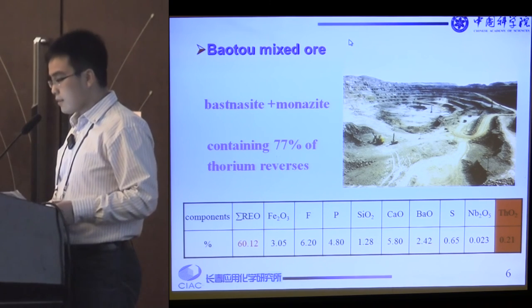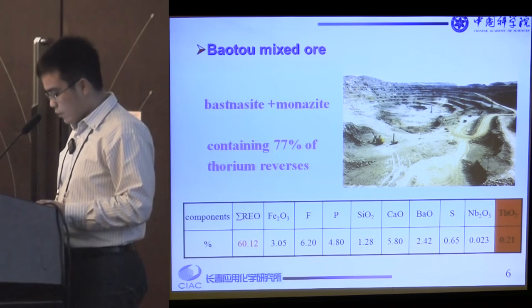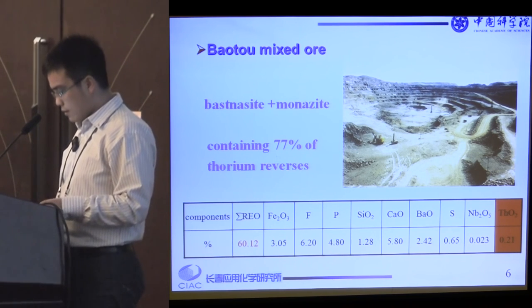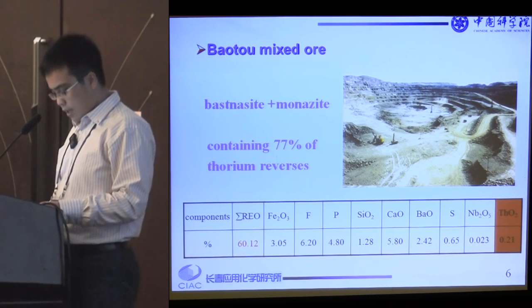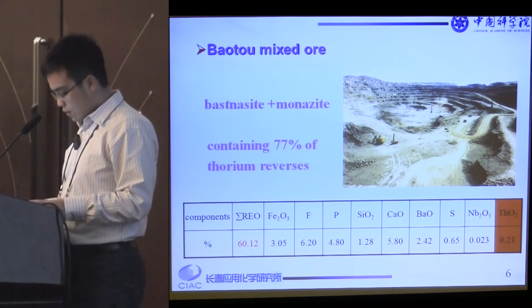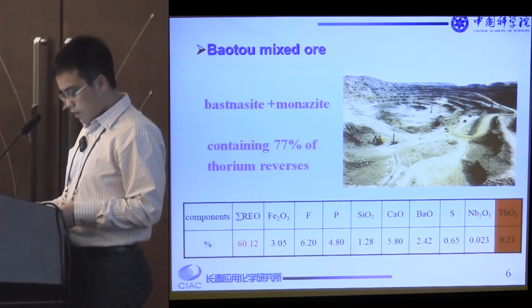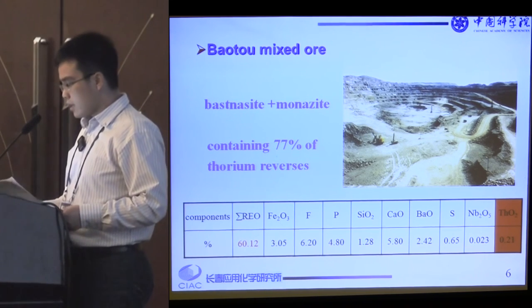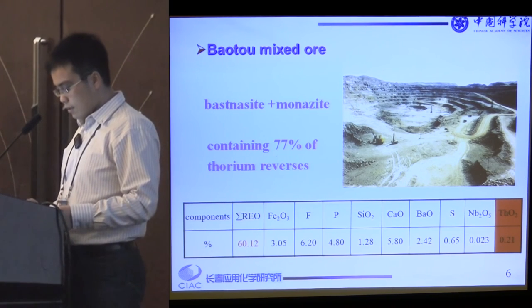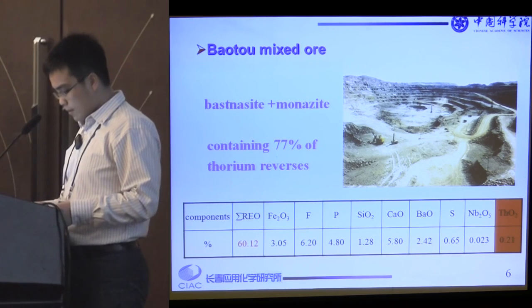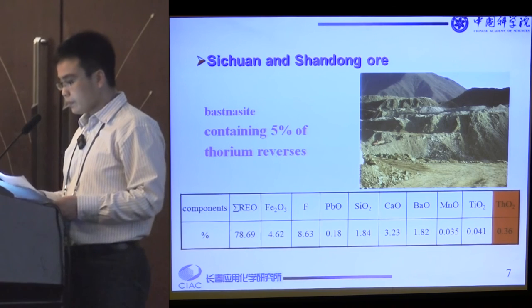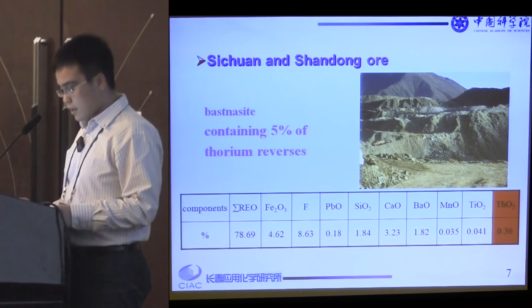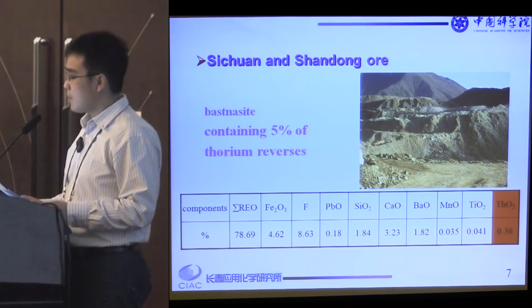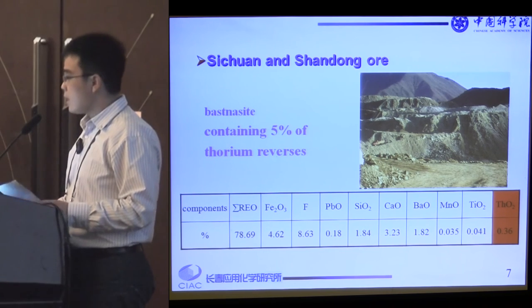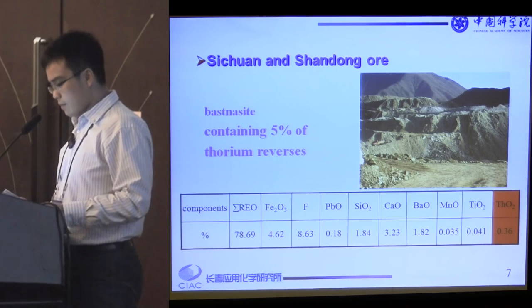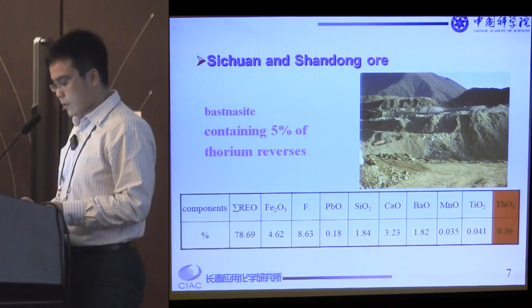Thorium resource in China exists mainly in three areas. One is Baotou in Inner Mongolia, and the other two are in Sichuan and Shandong provinces. The former is a mixture of bastnaesite and monazite ores containing about 77% of thorium reserves. There are more than 60% rare earth metals and 0.21% thorium in the mixed ore. The ores in Sichuan and Shandong are mainly bastnaesite containing about 5% of thorium reserve. There are more than 78% rare earth metals and 0.36% thorium in the bastnaesite ore.